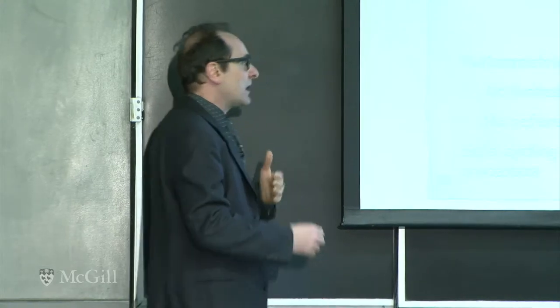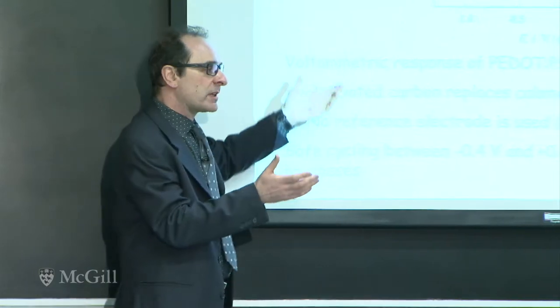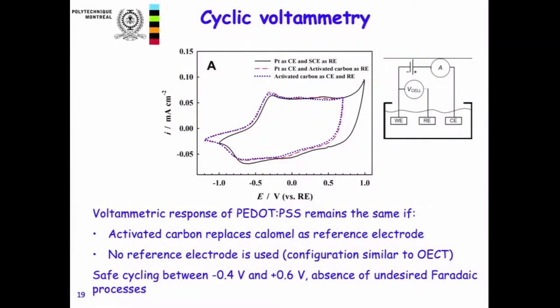So the way to show that this material works well is to compare it with an electrochemical cell where we have three electrodes: counter, reference, and working electrode. You just replace the reference and the counter with carbon paper, and you see that the cyclic voltammetry curves overlap.